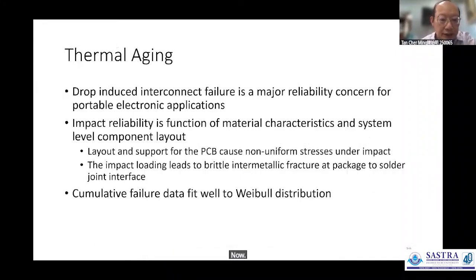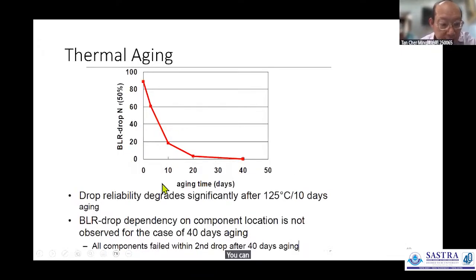Now, thermal aging is another thing, especially for molding compound. Before we go to that, as I said, the Cu3Sn is very brittle, so when you drop it, it will actually break. You can see this is an experiment people have done. They put the solder at 125 degrees C for 10 days. For the drop test, 50% of the samples will fail, which is still quite high. You need to throw about 90 times before they break.